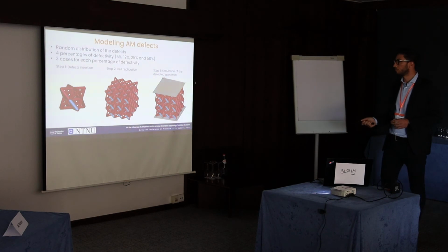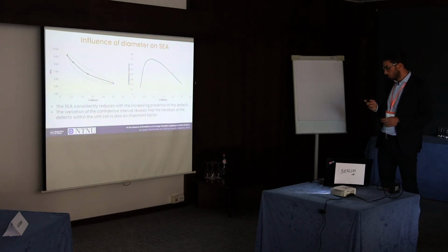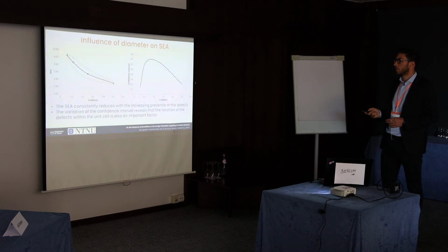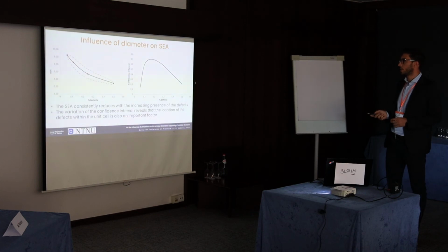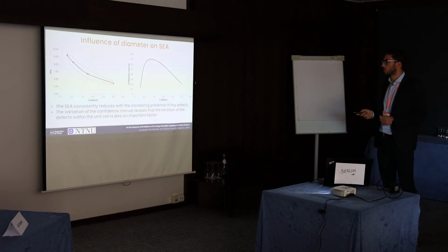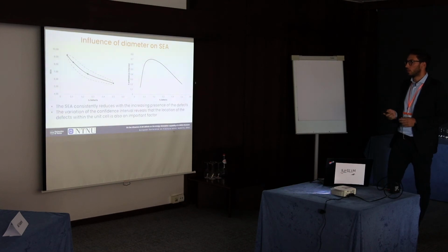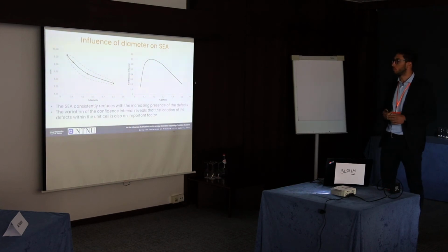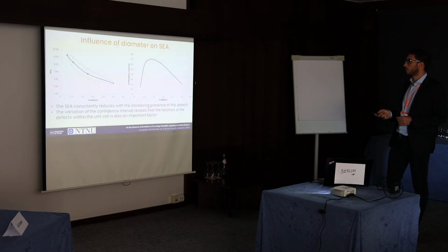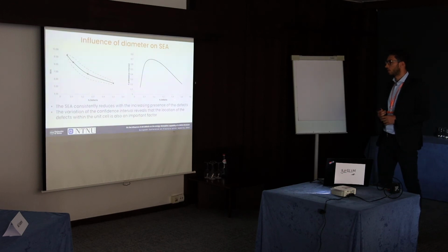defect that we considered. And here you can see the results of this numerical analysis, where you can see that we have a consistent reduction of the specific energy absorption with the increase of the defectivity. Also, you can appreciate that there is a consistent variation of the confidence interval from the analysis that we made with the random distribution of the defects. And you can see that the confidence interval tends to increase for a middle range of defectivity, while it is a bit lower at the extremity of the domain.